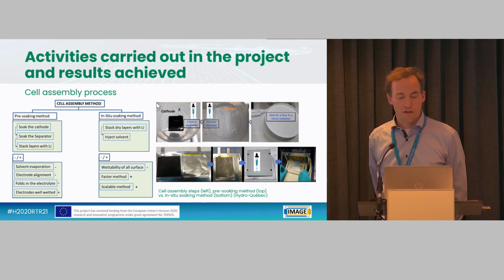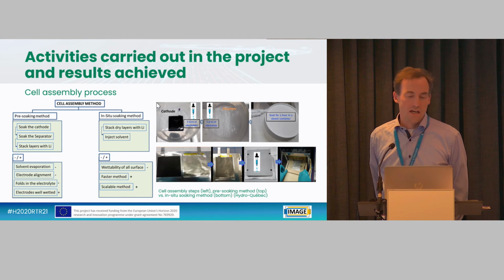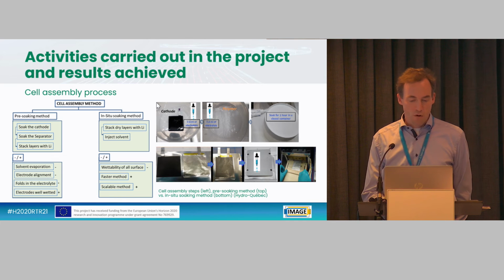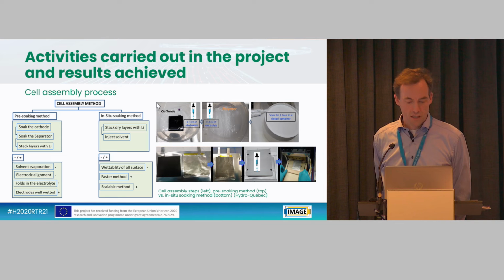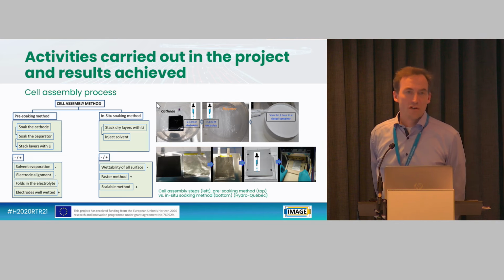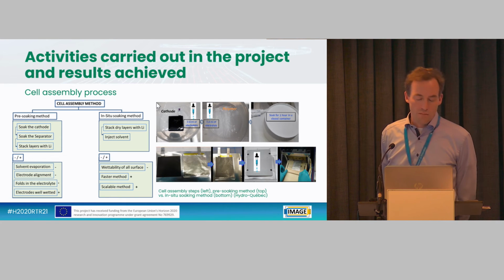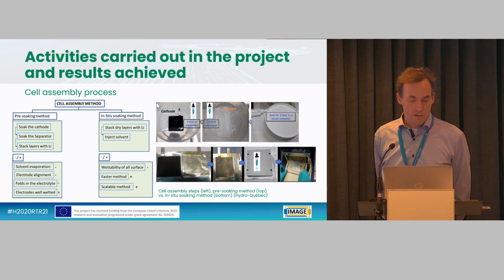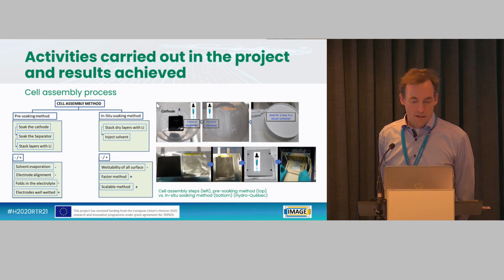Or you go for the other method: you do an assembly of the dry components first and put in the electrolyte afterwards. The second method is closer to what we have in state-of-the-art cell manufacturing today already. It also turned out that with this method we get the more reliable cells, the more reliable results. However, the process is still far more complicated than with state-of-the-art cells.